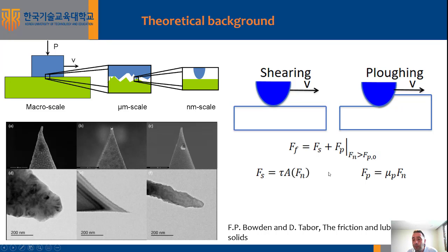So in any case, if we combine both contributions, we would obtain for the friction force that it is simply the sum of the shearing force and of the plowing force above a threshold value of the normal force. So if you want, the shearing may be brought in analogy with adhesive wear, while plowing is the analog to abrasive wear.